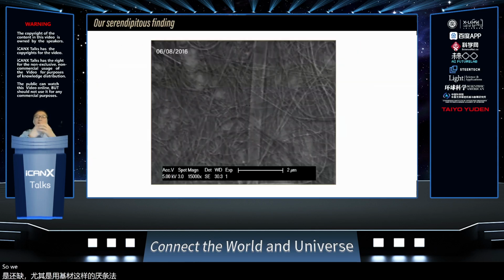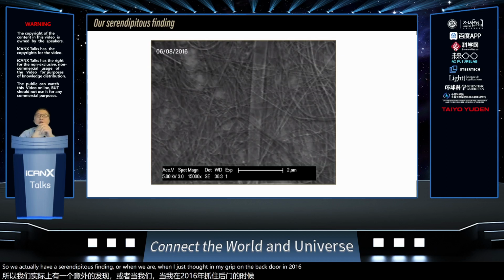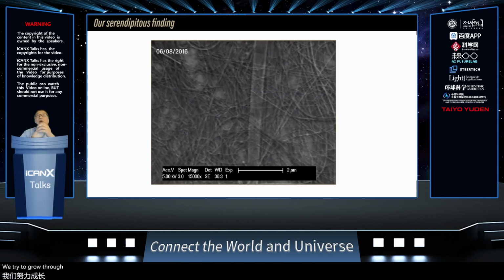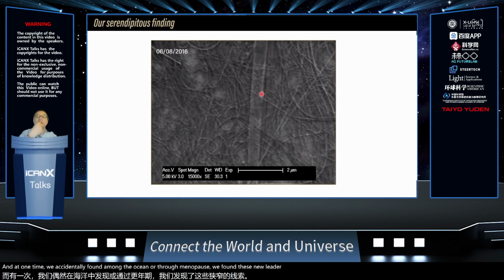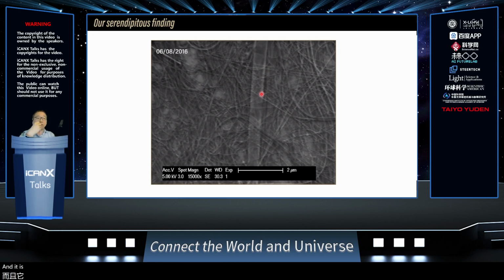So we actually had a serendipitous finding. When I just started my group back in 2016 at Purdue, we tried to grow tellurium nanowires following the procedures reported in the literature. At one time, we accidentally found, among the ocean of tellurium nanowires, this nanoribbon. At that time, this ribbon was only around 100 nanometers wide, and it inspired us to explore why this happens, because this had never been reported before.